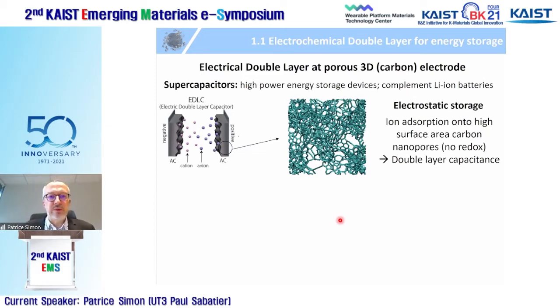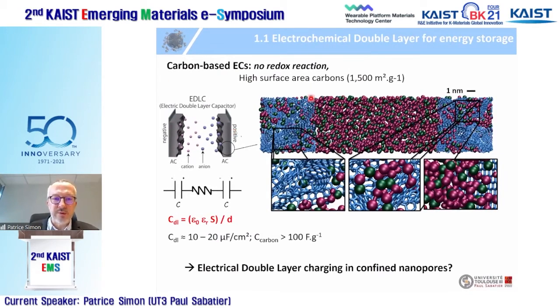As you may know, supercapacitors are high power energy storage devices. The charge storage mechanism is only based on electrostatic storage by ion adsorption onto high surface area nanoporous carbons. There is no redox reaction; the electrode material here is only porous carbon. This is a modeling representation of a porous carbon electrode, the electrolyte, and the second porous carbon electrode. You can see that when you polarize the system and inject positive charge onto a carbon, then anions of the electrolyte will go into the positive electrode. This is what you see here. All these anions are going inside the pores and adsorbed into nanopores. And by doing that, there is no redox reaction. You just charge a double layer capacitance.